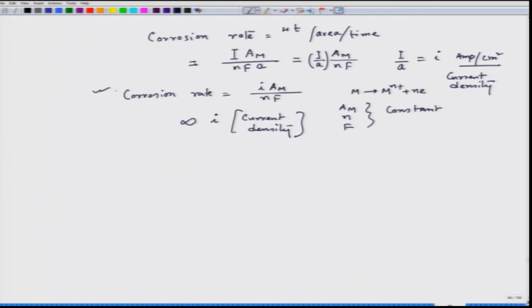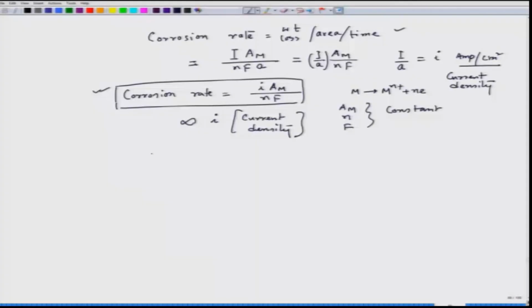Now, once we get this idea, we can see that it is basically in the form of weight loss per unit area per unit time. Now, we have seen that in those cases where the dissolution pattern is localized, we have to use a different way of expressing corrosion rate, which is nothing but the penetration depth divided by time. So, we can convert this expression in the form of the depth penetrated per unit time by simply dividing this corrosion rate with the density of that particular metal.